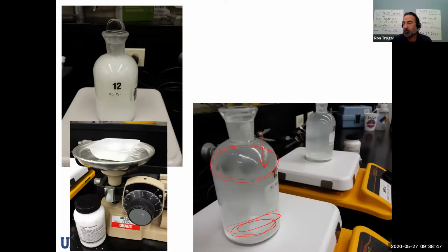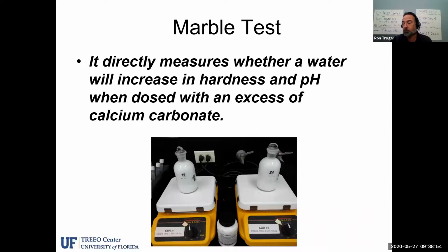What we're actually doing, if you don't mind, I'm going to back up just a second here, and I want to offer to you all that we need to measure several parameters before we add the lime to the water. What we're going to measure is the initial water. We're going to measure the pH. We're going to measure the hardness, known as calcium hardness. These are things that we're going to measure of the initial water. And then we're going to measure the alkalinity. Now, this could be the total alkalinity or the total and phenolphthalein alkalinity if we would like, but basically the total alkalinity. We're going to measure those three things on the initial water that we're sampling, and we're trying to see if it has the ability to be scale forming or if it's corrosive.